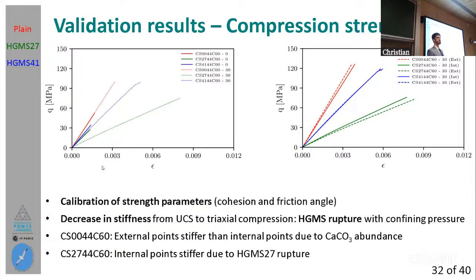And why is that? Because we are applying the confining pressure. During the confining pressure, the spheres are breaking. Since the spheres are breaking, they are transforming somehow into porosity, and in the homogenization model this decreases the stiffness of the material. Then the cement paste with HGMS 41 is somewhere in the middle, because we didn't break that many spheres, so we have a behavior in between these two. If we take a look at the image on your right, you will see the results for 30 megapascals of confining pressure on the carbonated specimens, internal point in solid line and external point in dashed line.